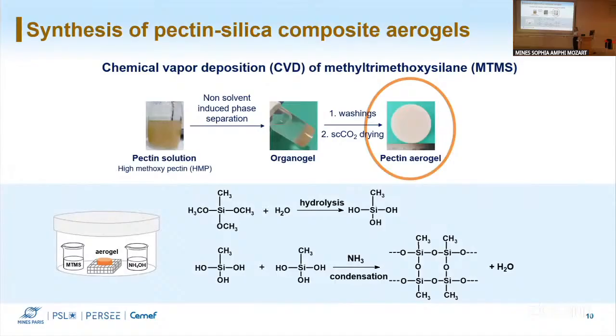And we said that it will be very hard to distinguish, even with silicon NMR. So we didn't continue measuring the data. So we don't know if it's covalently cross-linked, because chemically speaking it could graft covalently, but we don't know if it does, or if it is just the polymer that forms around the fibers. Yes, with a layer.